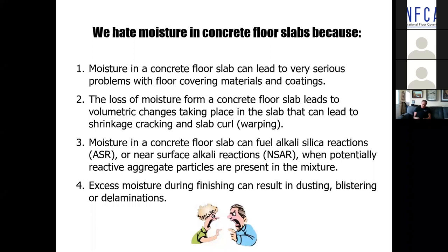Moisture in concrete can also, if potentially reactive aggregate particles are present in the mixture, feed that process referred to as alkali silica reaction or near surface alkali reaction. These are aggregate particles that really shouldn't be in the concrete mixture, but it happens all too frequently. And we could get into explanations as to why that would happen another time.